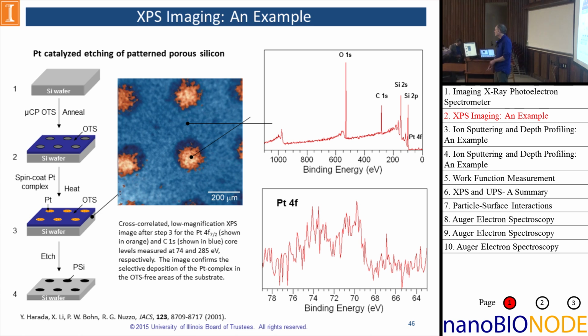Now here's an example of some microcontact printing that was done here at the university, where they wanted to confirm this step, that the platinum catalyst that was being used to etch the porous silicon pixels was actually selectively depositing inside these little circles. And so by doing two XPS images, carbon in blue and platinum in orange, we were able to see that the platinum was located inside the circles as desired.